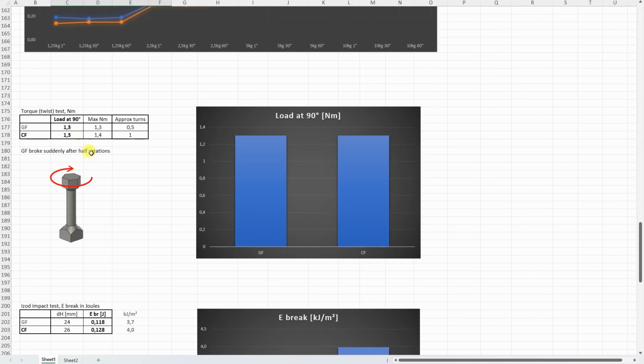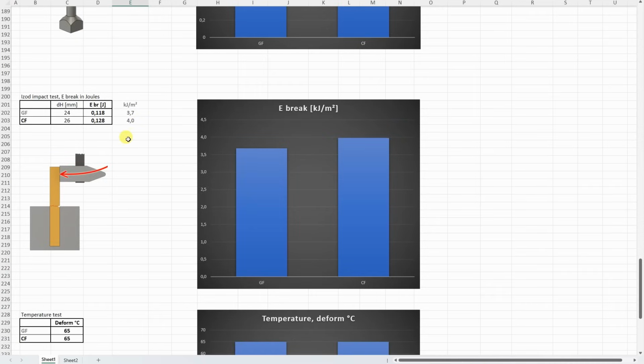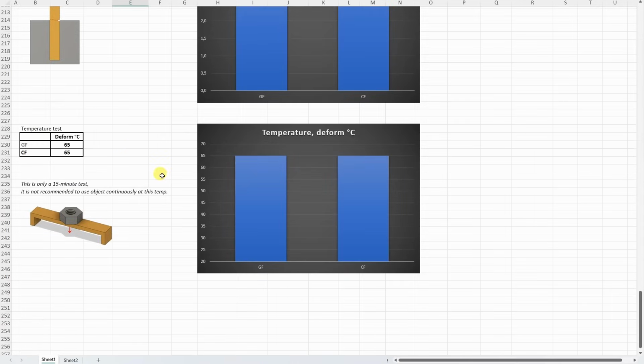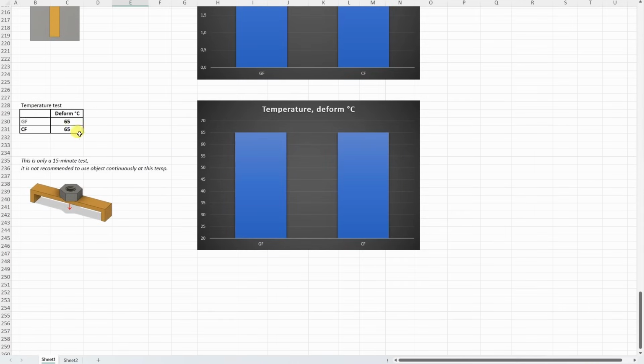On the torque or twist test, the load at 90-degree angle is more important, and it was equal in this case, but yes, glass fiber was very brittle. After half rotation it snapped in two pieces. On the impact test, very similar values, but in both cases these are very brittle materials actually. And on a temperature test, it started to deform at approximately 65 degrees Celsius. It was hard to notice the exact moment of the deformation. It could be a little bit higher, but yes, they are better compared to the regular PLA.